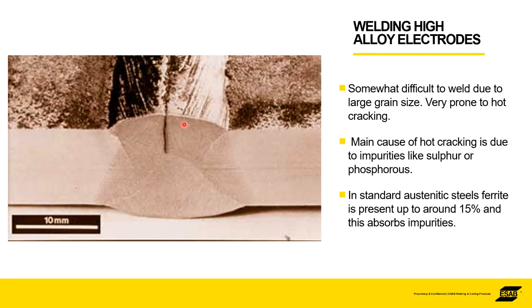There are a number of things that you can do to influence it, but essentially the weld doesn't have the strength to hold itself together as it's cooling down. So the thermal stresses induced by heating up and cooling down are more than the mechanical strength of the weld, and that's why it cracks on cooling. But I've got to stress, it is really with the super austenitics, the very highly alloyed grades, the nickel alloys, that kind of thing. With standard austenitics, this is not generally an issue because of the presence of ferrite.